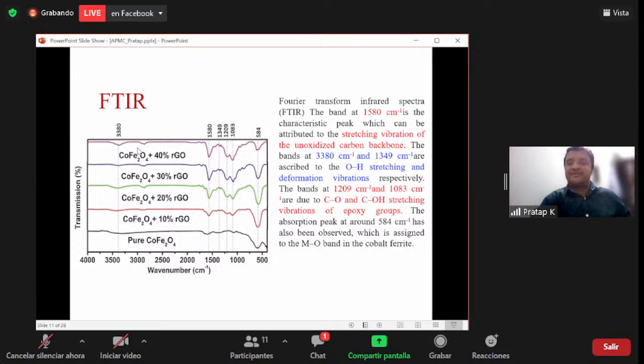So this is the FTIR data. The black one is pure cobalt ferrite. The red is cobalt ferrite with 10% RGO. Sorry, let me correct: black is the pure one, this is 10% RGO with cobalt ferrite, this is 20% RGO with cobalt ferrite, this is 30% RGO with cobalt ferrite, and this is 40% RGO with cobalt ferrite. You can clearly see that the peaks are prominent.